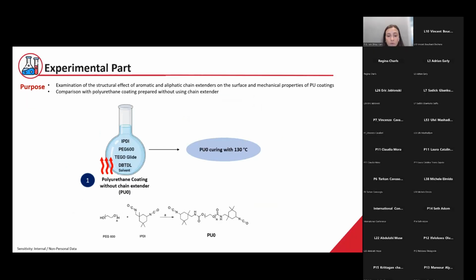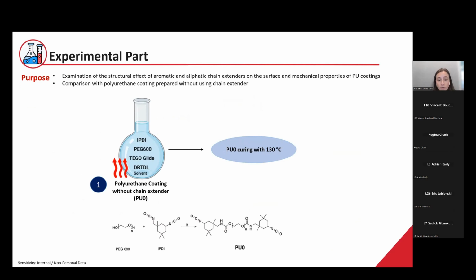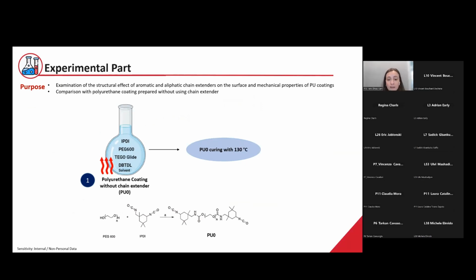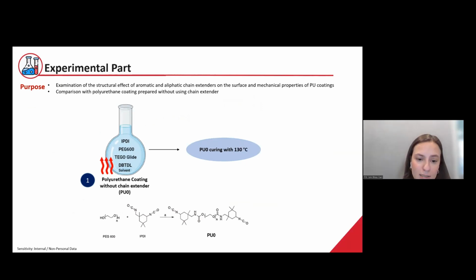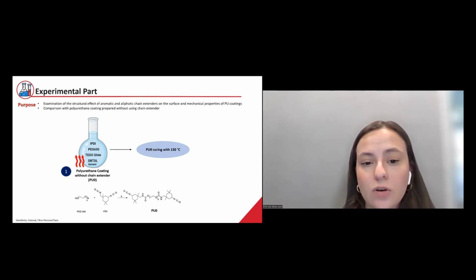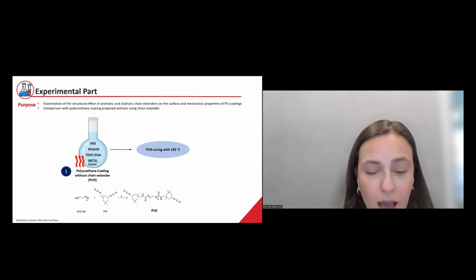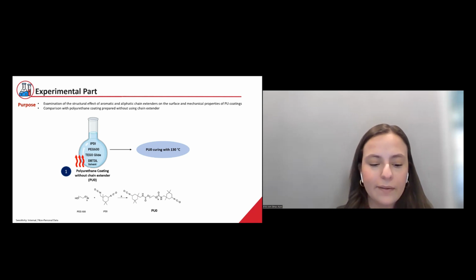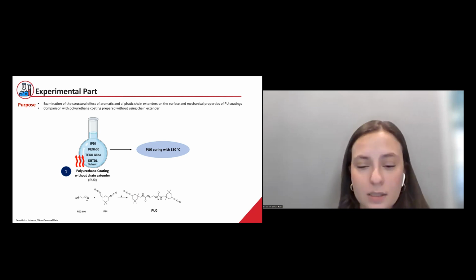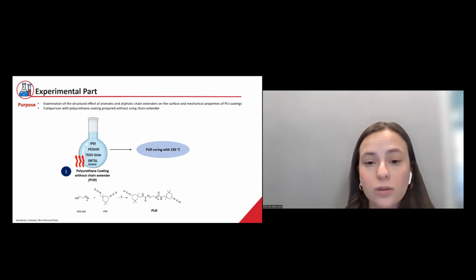In our study here, we have two different formulations other than the base coating. Our first formulation is our base polyurethane coating formulation that does not contain any chain extender, only the main components of the polyurethane. And we coat it on metal surfaces in the spin coater device and cure it in an oven at